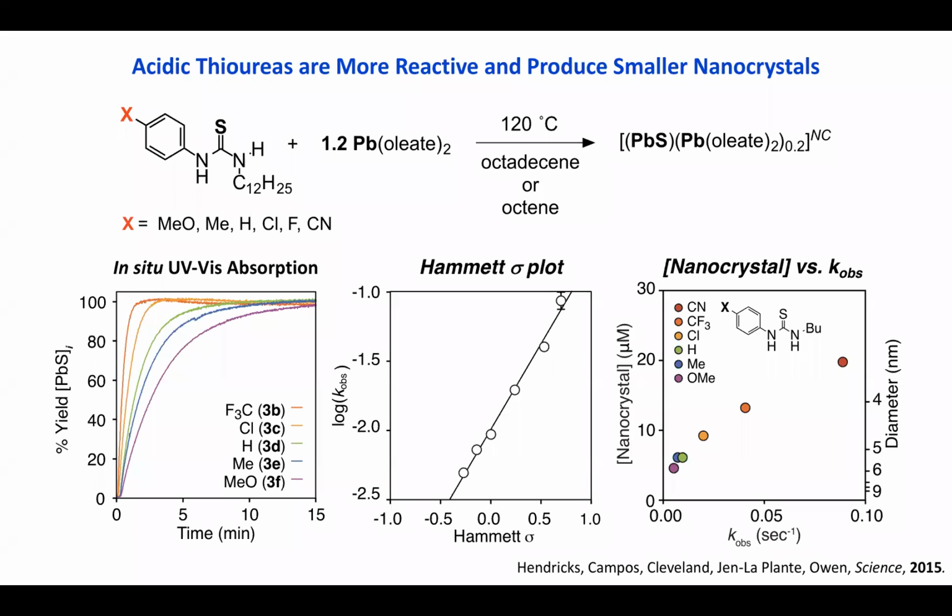All right, so here's an example reaction that we've been studying to death. It's the combination of thiourea disubstituted one here with lead oleate. We have a slight excess of lead because the stoichiometry of the lead sulfide you make has excess lead oleate bonded to the surface.